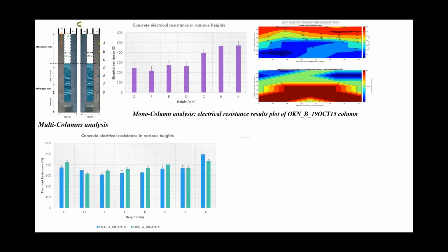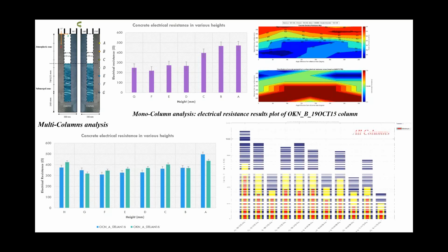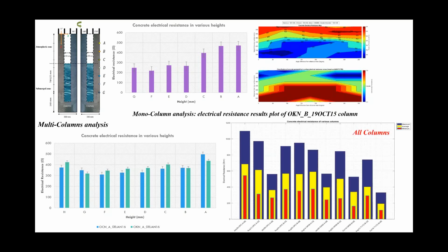One or almost 3 items that I realized is the effect of age. The samples that you can see have the higher values in the chart are the samples that I cast earlier, and they are older than the others. I also realized that the ones with the admixture have a higher electrical resistivity, and some of these samples showed that cover thickness also plays an important role. The ones with thicker cover thickness showed higher resistivity.